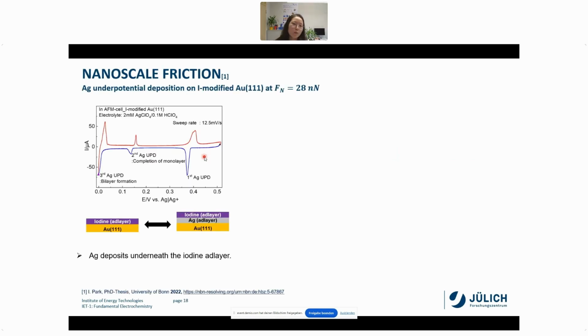Now I would like to show you an example which I measured during my PhD thesis in Bonn under the supervision of Professor Baltruschat. This sample is iodine modified gold 111, and the electrochemical system is a silver containing electrolyte. The silver will be deposited by a potential sweep or dissolved into the electrolyte again. But the interesting part is that silver will be deposited underneath the iodine, so iodine will stay all the time as a topmost layer. Now we are going to look at the friction data.